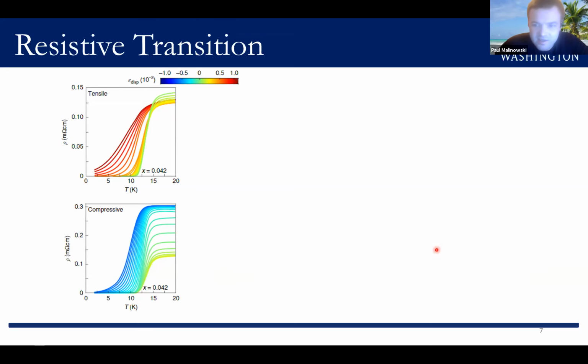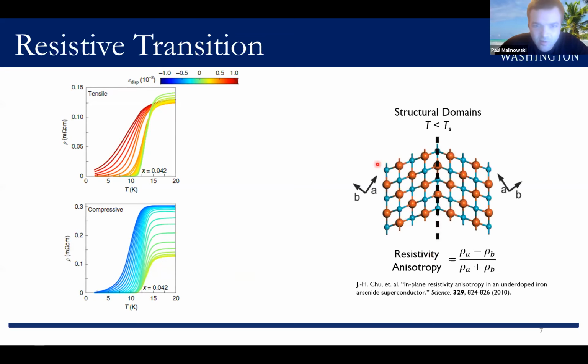Now, this is readily understandable due to the presence of nematic domains, which are present because for this composition, the superconducting transition occurs below the structural transition. So for small values of applied stress, the effect is just to align these twin domains while no individual domain experiences any strain. And the large resistivity change we observe can be attributed to the large resistivity anisotropy that's known to exist in the orthorhombic phase.